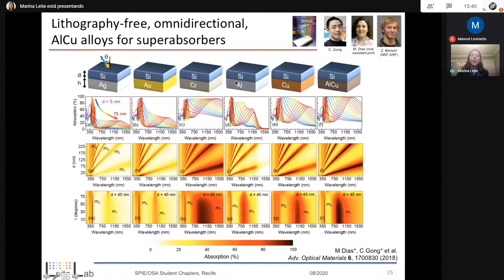Now, when we look at aluminum and copper, we thought, okay, there's something going on here. It definitely looks high for copper, but the combination of the two gives a much better response. So this is a 99% light absorption, and it's multi-wavelength, meaning we can shift this wavelength of very high absorption by simply changing the thickness of the silicon layer. The silicon layer here is represented by D. It varies between 5 nanometers and 75, and the metal just has to be optically thick.